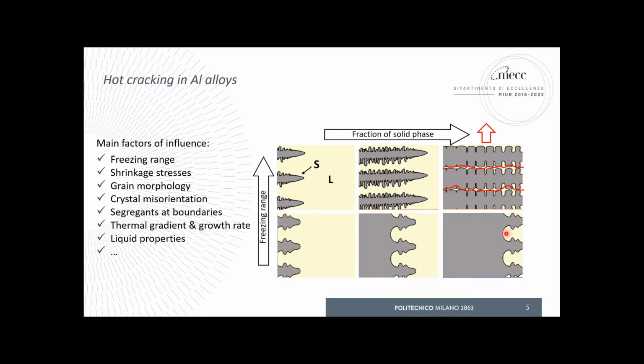Another strategy which could be very effective is to switch from columnar grains to equiaxial grains. By this method, we're going to have much more interface where the liquid pockets can spread around. The stress can be distributed in a different way, so that we end up having much lower cracking, or sometimes no cracks anymore.